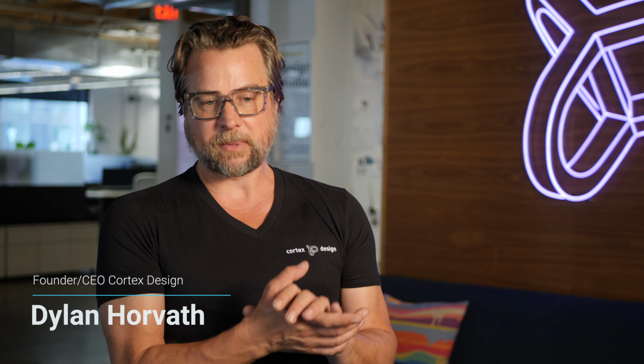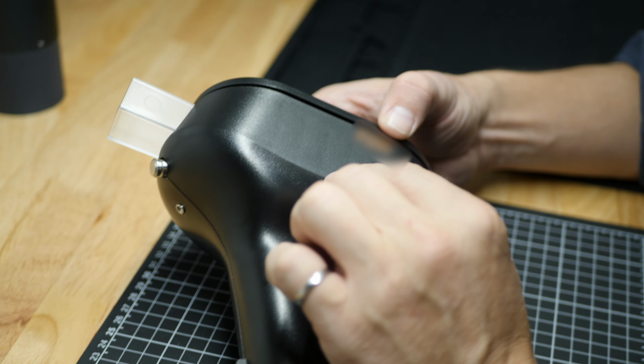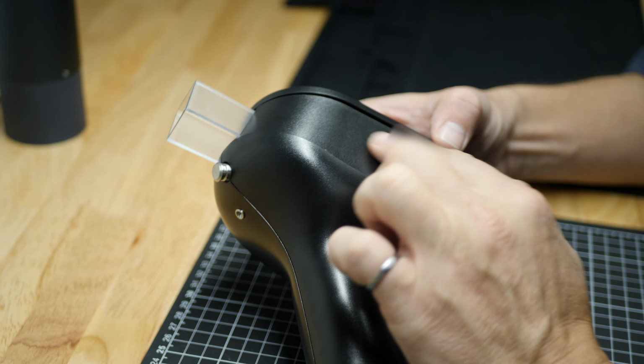Injection molded parts perform well when they're given the right amount of time to flow. So like a liquid plastic flows into a mold, and then that part solidifies. If you have non-uniform wall thicknesses, then things happen to the geometry as it cools. If you have a big mass of plastic behind an outer surface, that mass will cool slower than the rest of the thinner parts. And when it cools slower, it can sink. So you'll literally have sinks in the part.